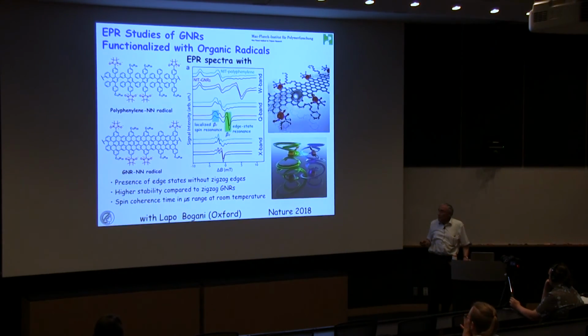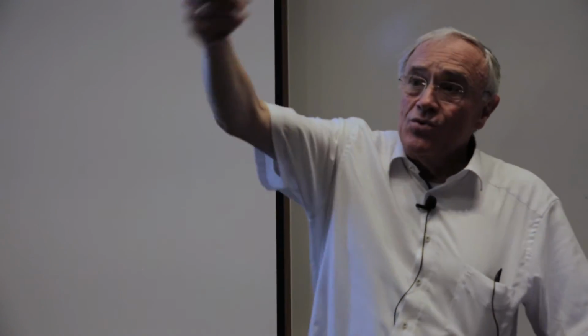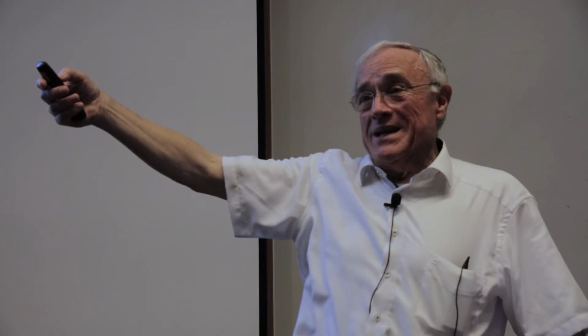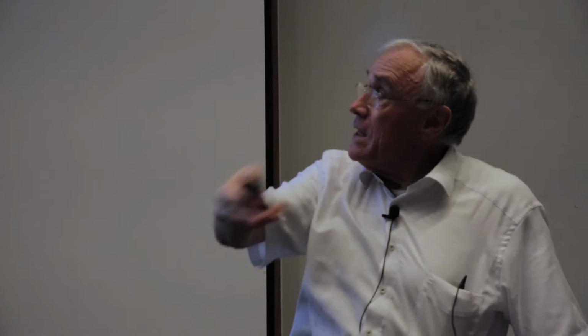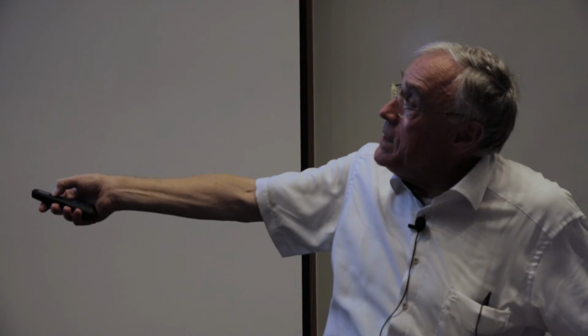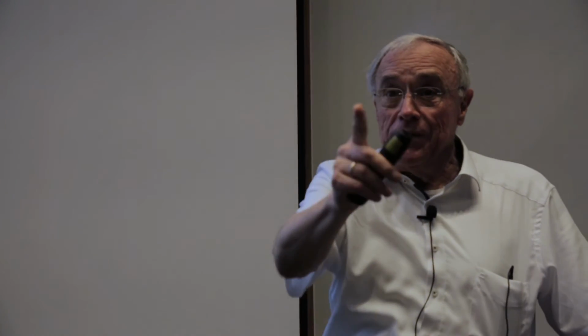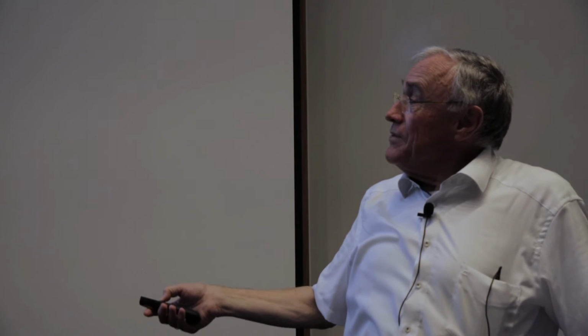And here, I think, is an example where I believe the credit needs to go to Lapo Bogani. Let me explain. When we made these, we had beautiful cases of proving edge localized states. We could even calculate that in DFT with Kohn-Sham orbitals, but the material was not stable under oxygen. And then Lapo suggested to Akimitsu, well, we use your good old solution-made graphene nanoribbons, but we add spin-bearing centers, and there you transfer the spin density, and this is what gives you spins on your semiconductors. And the ESR told us that we have now coherence times in the microsecond range at room temperature.